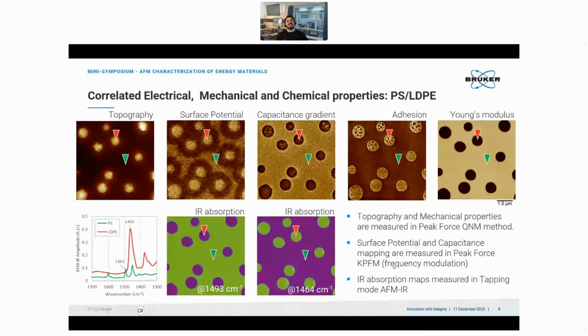Now, if you use a system that has, in addition to that, the capabilities of doing the IR, for example the ICON IR system, then similarly to before, you can map, after you do local spectroscopy, the chemical ID. So when we do local spectroscopy at these different points, obviously at the red point, where we have the LDPE, we see peaks that correspond to the absorption of LDPE. And on the polystyrene, we see peaks that correspond to polystyrene. So we can make our choices such that we can discriminate between the two materials. So 1493 will show us that the polystyrene is the one that's absorbing. So higher contrast here is the green. And when we switch again the wave number of the laser pulse, then we are looking at the absorption of LDPE.